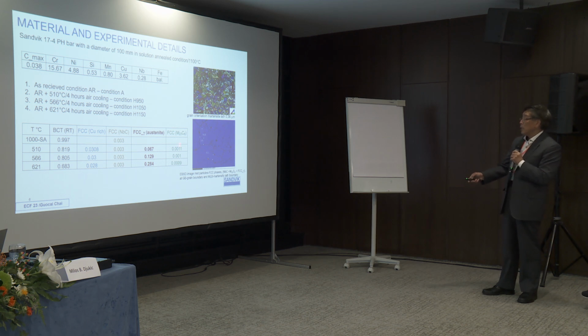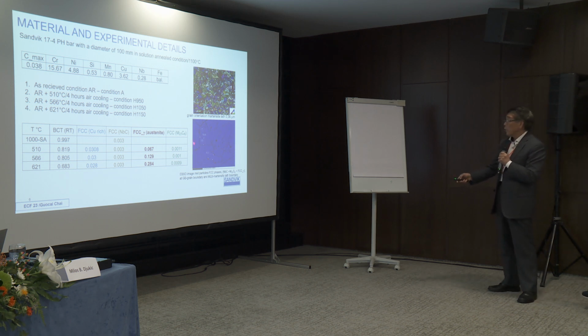Then there are M23C6 carbides, and the temperature influence is also small. What happens is just the austenite phase. With increasing temperature, the austenitic phase increases. We can find where this austenitic phase is: it's mainly at grain boundaries or martensitic lath boundaries. So they are quite important. I will talk about it later.